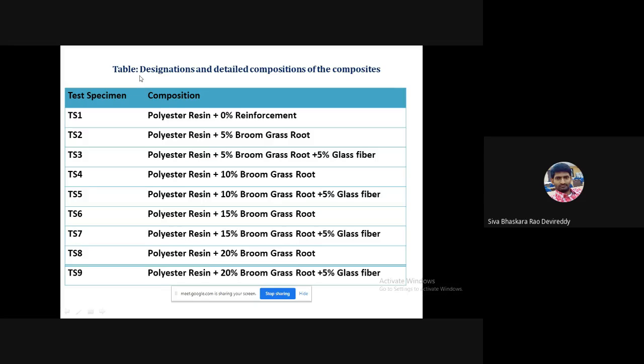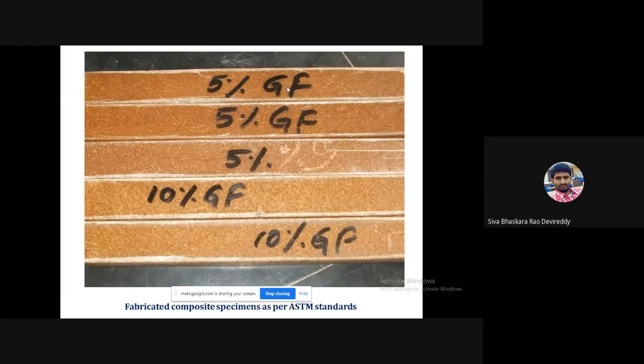The details of the composite materials fabricated in the present work are shown in this table. A total of 9 sets of composites were fabricated. The first set is neat polyester resin without any reinforcement material. From the second set onwards, the broom grass root particulate content was increased gradually with 5, 10, 15, 20 percent, and other sets are with addition of glass fiber. With and without addition of glass fiber, the mechanical and physical properties were studied. These are the composites fabricated by using this hand lay-up technique.